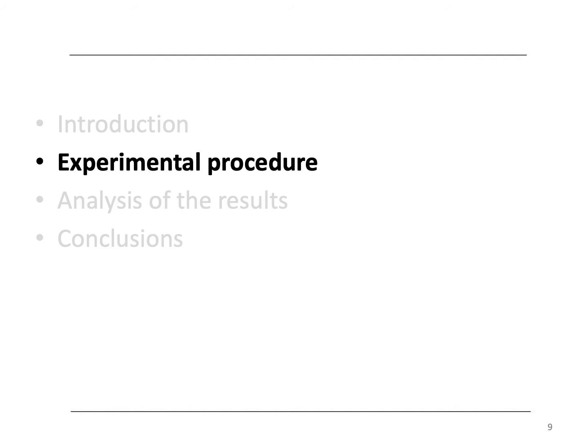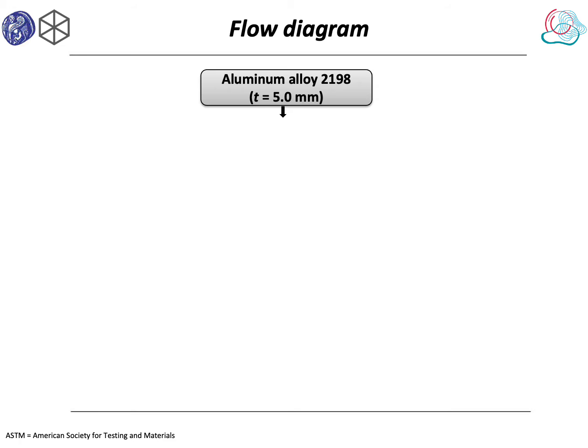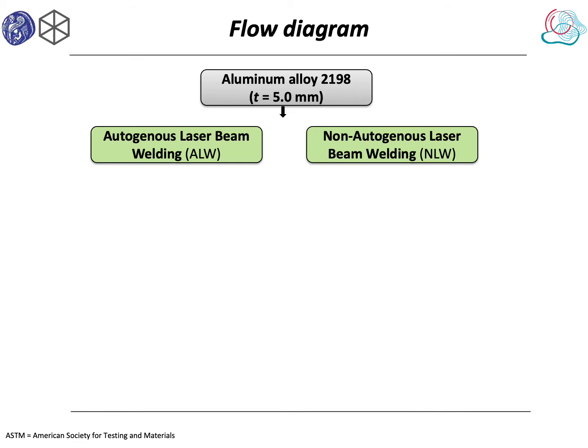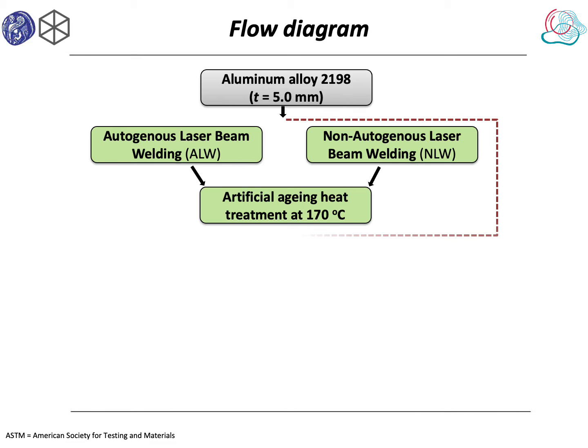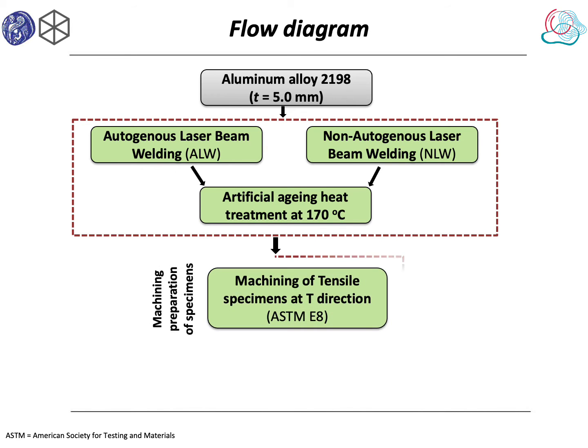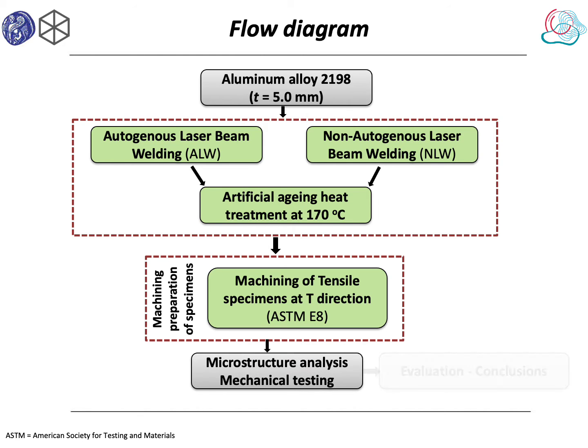Continuing with the experimental procedure. We investigate aluminum alloy 2198 with 5 mm thickness. Some of the sheets were autogenously laser beam welded, and some of the sheets were laser beam welded with filler material. Then the sheets were post-weld heat treated at 170 degrees. From both welds, tensile specimens were machined, and then we had the microstructure analysis, the mechanical testing, the evaluation, and the conclusions.